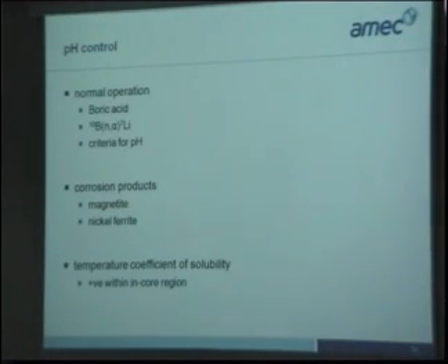But on the chemistry of this, on the primary side, instead of, during a fuel cycle, gradually pulling the control rods out to compensate for the fuel burn-up, it's usually done with what we call a chemical shim, and that's boric acid. So boric acid is in fact dosed into the primary circuit, and as the fuel's burnt up, the boron's taken out through the cycle to compensate, and this saves moving control rods up and down all the time.